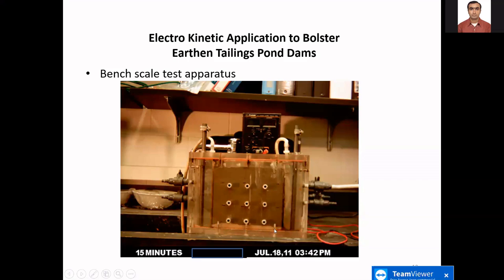At the bottom of the test cell, I provided for a layer of sand and a small layer at the electrode reservoirs, such that if water is expressed coming out of the compressed tailings, it would flow under gravity through the tailings undergoing treatment, as it flowed from this potential here down to this potential, and it could be collected for sampling and chemical analysis.